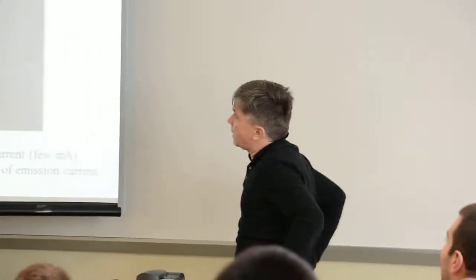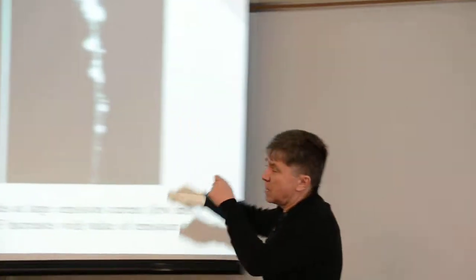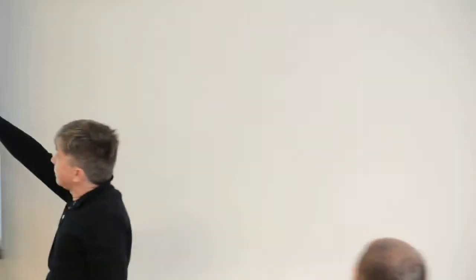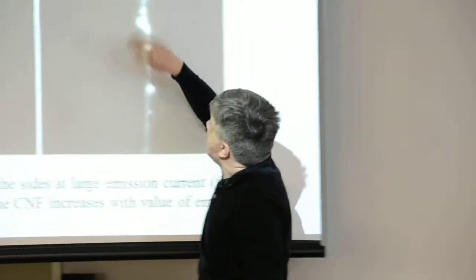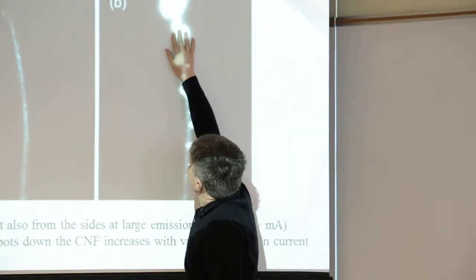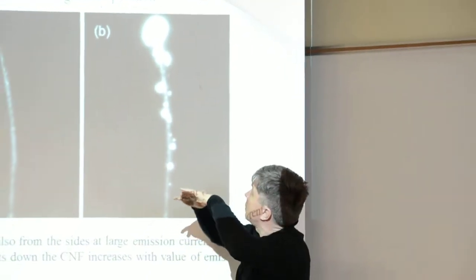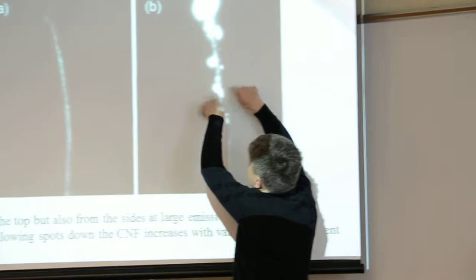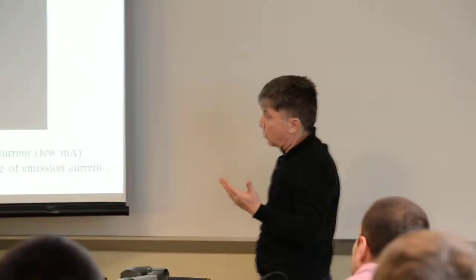How do we know the tube gets hot? You sweep up, stay there for lunch. But if you approach too much, the field is higher, so the tube gets hotter. This is what we see when we see the fiber here. It looks messy at the top because it was chopped with a razor blade. The tubes are stuck at the top. Then we see the thing glowing. This is the space charge emitting regime I was talking about. You emit so much you form a plasma from the tip. Then it starts growing. Your current saturates. As you increase bias, you see those glowing spots start going down the fiber. What can come from the top is saturated. There's no way to get more electrons from there because of the plasma. The electrons in the tube say, I'm going to emit from the side then. As you do that more and more, as you put more bias, that lightning thing just goes down. Eventually it can fry your tube, your fiber.